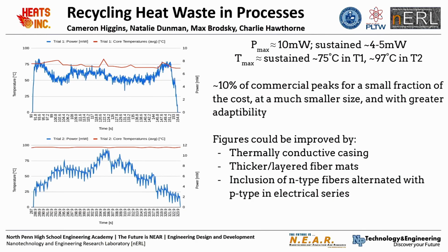Even for a baseline, though, our results were very, very promising. We were able to maximize our power output at around 10 milliwatts while sustaining reasonable temperature on our computer. And this is promising because though it is only about 1/10 of our commercial peaks, our TEG was made with much fewer materials. It was much cheaper to produce. It is also much smaller, and there are many modifications that can be made to it to increase its efficiency, such as using a thermally conductive casing, using thicker fiber mats or layering them, or including an N-type fiber in alternated electrical series with the P-type fiber.